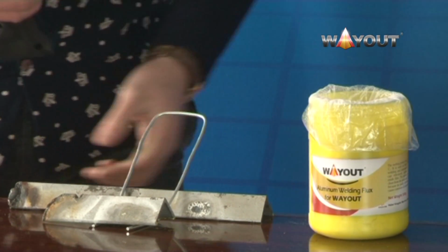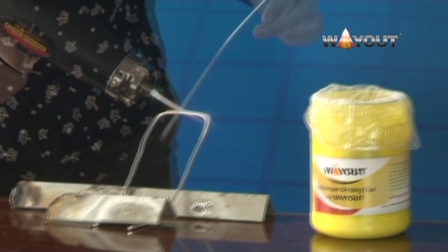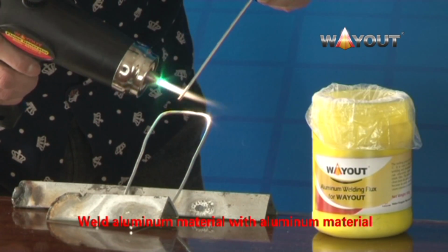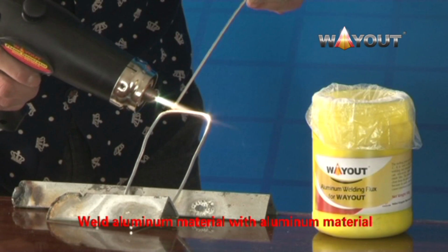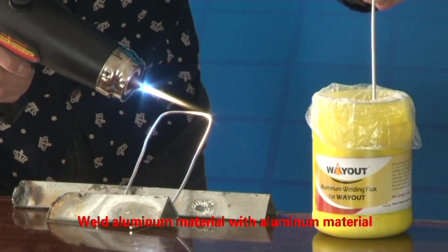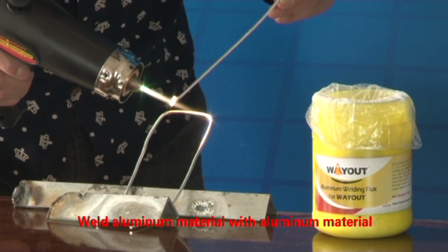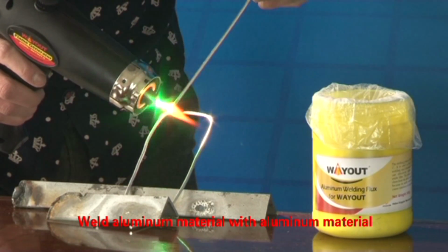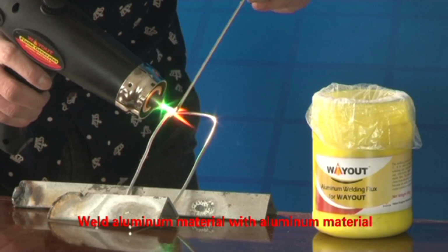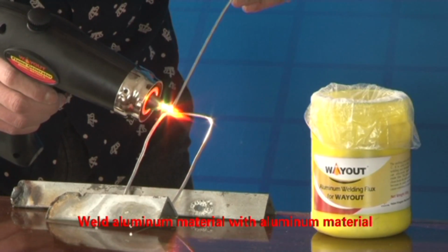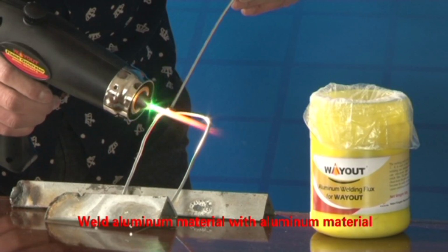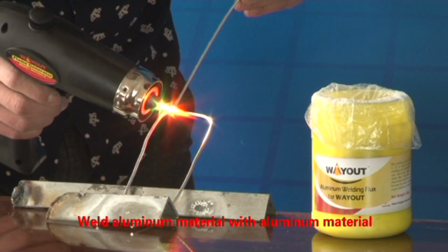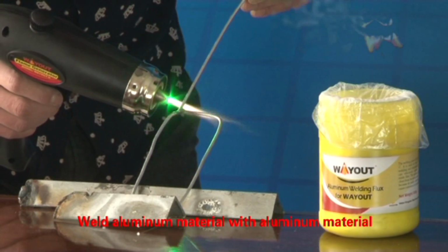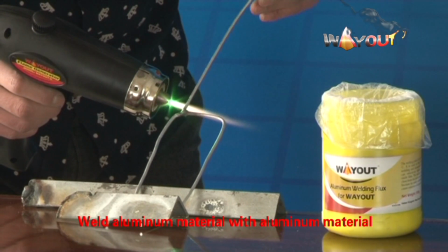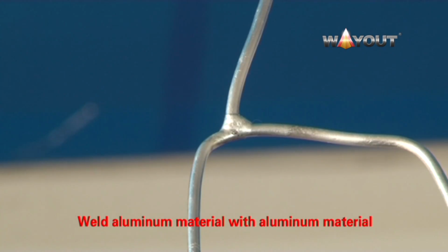2. Weld aluminum material with aluminum material. First, heat the workpiece and dip the part to be welded into welding flux. The melting point of this flux is about 560 degrees Celsius. It is used as flux in aluminum welding and aluminum alloy welding. It can effectively destroy the aluminum oxide film. The residue must be washed clean from the metal surface after welding, because it easily absorbs moisture, which can cause corrosion of aluminum in air. The welded workpiece is clean, bright, and solid.